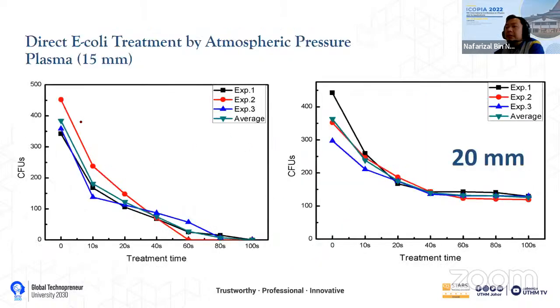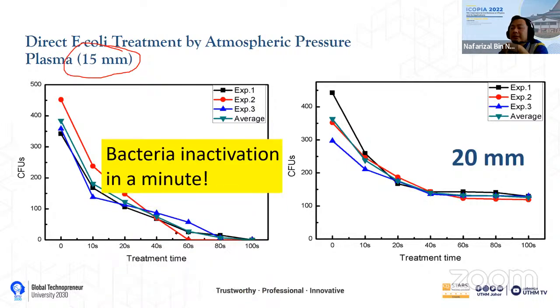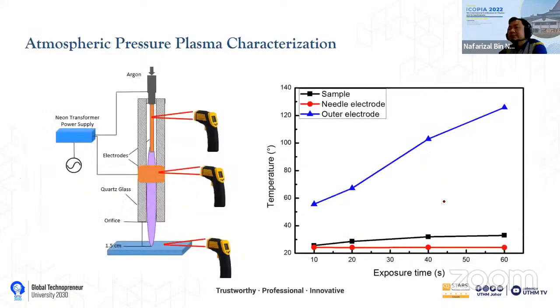So this is the summary. We repeated the experiment several times. We actually changed the distance between the plasma and the E. coli bacteria. On the left is at 15 mm, where in less than 1 minute you can see the bacteria is inactivated. If we put a little bit more distance, like 20 mm, you can see the bacteria is saturated at about these numbers, right? So we need to fine-tune the distance as well.